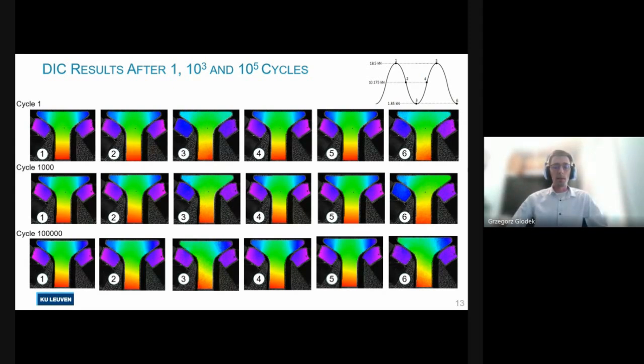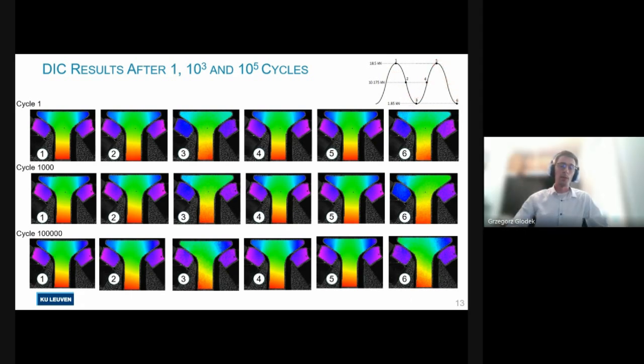But in one case, the DIC analysis was repeated after 1,000 loading cycles and after 100,000 loading cycles. So the test was stopped, and then 2 loading cycles were applied slowly while taking pictures for the DIC analysis. And here we can see the results of that. The figures show the vertical displacement of the sample and the pads. So we can see that at the minimum load, there is some asymmetry in the sample, but at the maximum load, there are no such abnormalities. So when the stresses are the highest, the setup is symmetric.